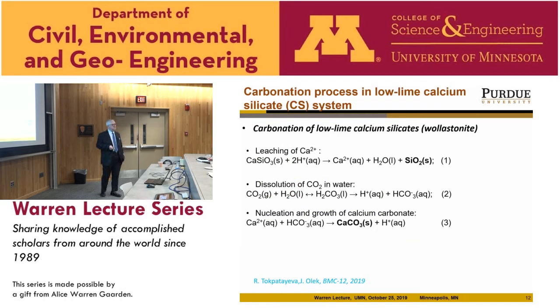So carbonation is a process that happens to every concrete. In fact, concrete carbonates naturally. There is a lot of calcium hydroxide as a byproduct of cement hydration. That calcium hydroxide will carbonate. And over time, there is a danger that if the carbonation depth is too deep, or if the concrete carbonated to the level of steel, you will have a problem with corrosion of reinforcement, because the steel doesn't corrode in concrete because it's being passivated by a highly alkaline environment of the pore solution that surrounds the steel rebar. But the carbonation actually leaches out calcium hydroxide. Leaching of calcium creates the SiO2 or silica gel, and pH drops and rebars will start corroding.